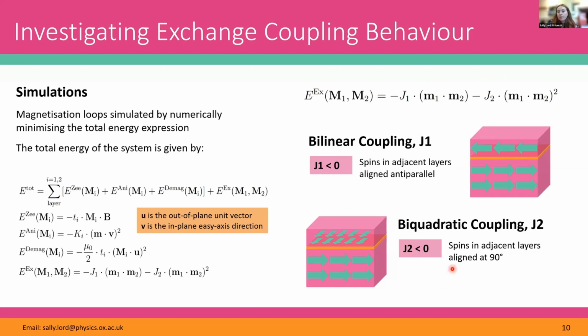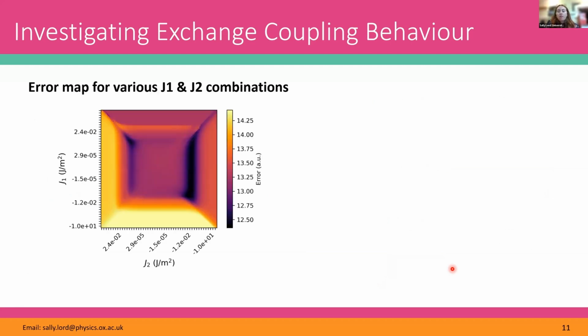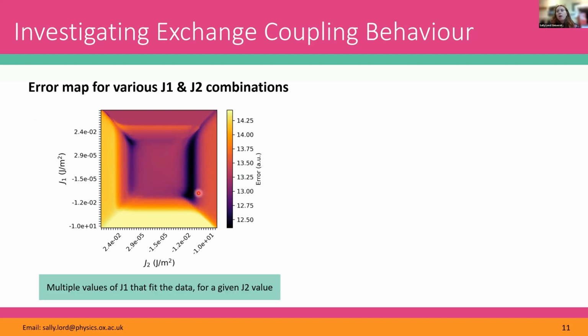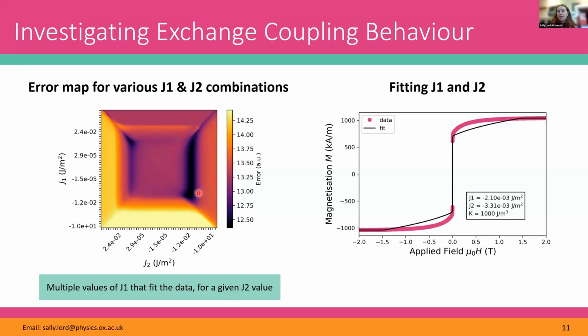And in order to work this out and quantify it, we simulated magnetization loops and then fitted them to the experimental data. And what we found was that there were multiple values of J1 and J2 that minimized the energy expression. So you can see here, there's a large range of values of J1, and a smaller range of values, but still quite a few values, of J2 that minimize the energy expression. But then we took these values of J1 and J2 and simulated magnetization loops with them, overlaid them on top of the data, and it looks pretty awful. It clearly doesn't fit. So then we were like, okay, why is that?